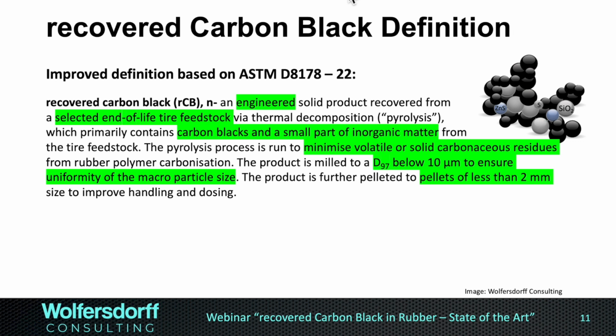Here is my improved definition based on that, because for me it's really important to stress recovered carbon black needs to be an engineered solid product recovered from a selected end-of-life tire feedstock. That we'll talk about when we get to the RCB rubber call to action by Michelin and Bridgestone, where they really stress that the product is defined by the end-of-life tire feedstock. Pretty much like, engineers say garbage in, garbage out. If you don't control the feedstock and we have just any kind of tires going in the pyrolysis, we cannot expect recovered carbon black. Then we have carbon blacks. We have a small part of inorganic matter.